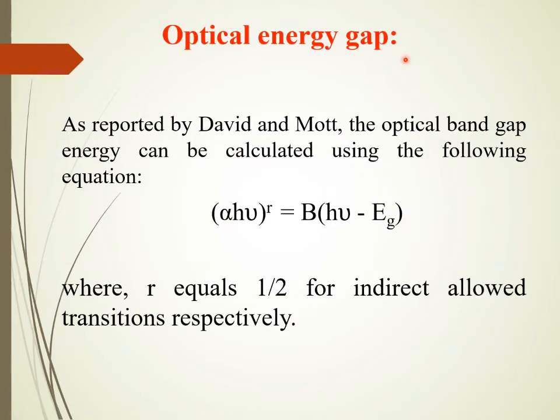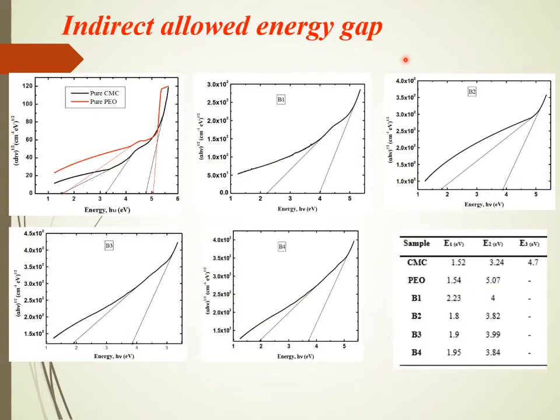Also, the optical band gap energy was determined using the Davis and Mott equation for pure CMC, pure PEO, and the blended samples. The following figure represents the variation of (alpha h nu) to the power half with the energy, and it is observed that CMC has 3 optical band gap energies, meanwhile PEO has only 2 band gap energies. And also, as a result of blending, the blended samples have 2 optical band gap energies, and the sample B2 possesses the lowest optical band gap energy.